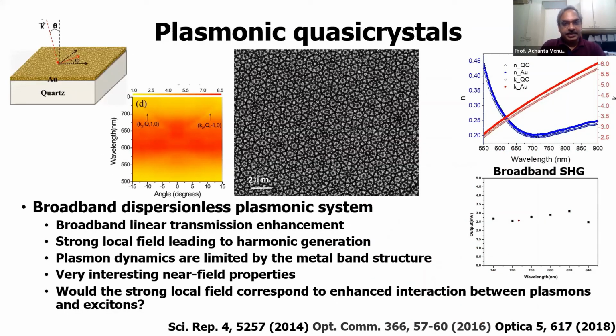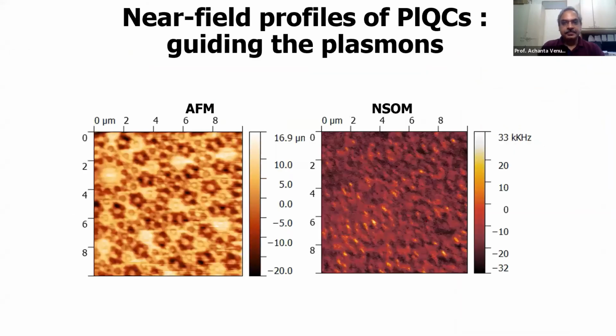We demonstrated such structures where we showed that you can get almost 3 orders of magnitude enhancement in the local electric field. So you can generate second harmonic, so the nonlinear properties are also possible in this. They have n and k values very similar to the bulk unpatterned metal, but they have very unique properties. They have a very broadband response, which is polarization and launch angle independent, and generates nonlinear harmonics. Higher harmonics are also possible to be generated using this.